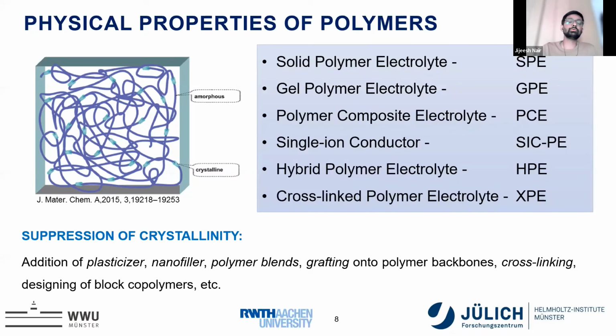And this led to several kinds of systems like solid polymer electrolytes. Even though this is not the ultimate classification, you can see that you have solid polymer electrolyte where no solvents are used, and gel polymer electrolyte, which is mostly coming up industrially, even for EVs or mobile phone applications, in which a small amount of solvent is used.